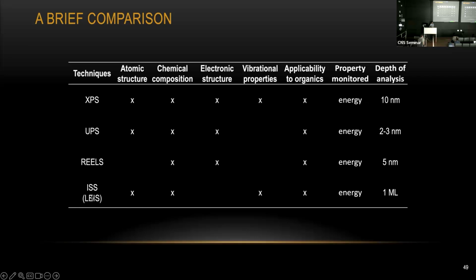For ISS, it still gives you some elemental information, but you can see the sampling depth is only about 1 monolayer. So compared to XPS, this ISS, some people call it LEIS, low energy ion scattering, is much more surface sensitive compared to all these measurement techniques. So for ISS, you can try to determine your surface coverage.